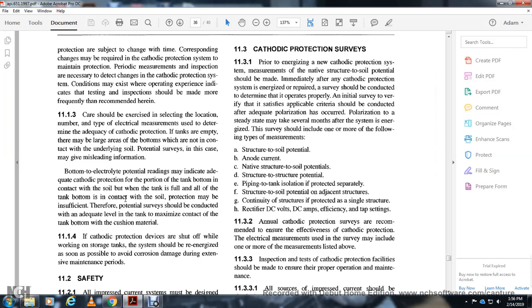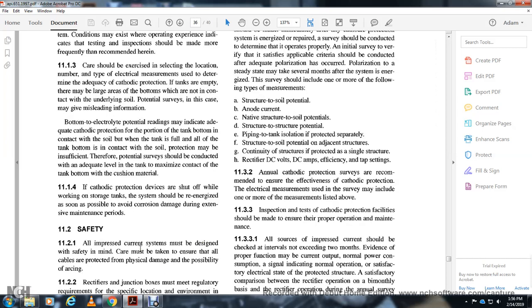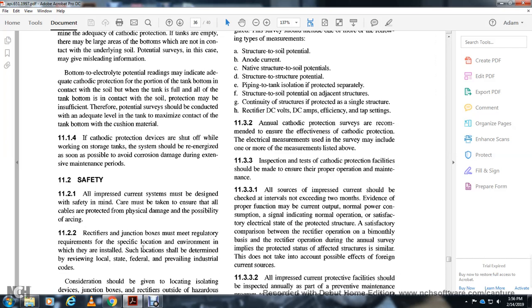Potential readings at the bottom with the electrolyte may indicate adequate cathodic protection on a portion of the tank, while at other portions of the tank bottom in contact with the soil, the protection may be insufficient. Therefore, potential surveys should be conducted at an adequate level of the tank to maximize contact with the tank bottom cushion material. If the cathodic protection device is shut off while working on the storage system, it should be re-energized as soon as possible to avoid corrosion damage during extensive maintenance periods.